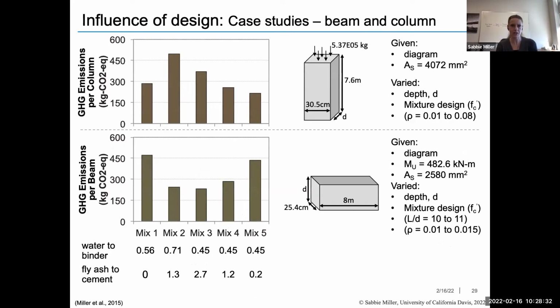So just to show you that as an example with reinforcement, these are very highly simplified members that I'm showing. We have a concrete column on the top and a concrete beam on the bottom. In this particular case, I'm showing them with the same reinforcement level. But basically what I want to emphasize here is that it's 5 different concrete mixtures with different water to binder ratios, which are what are highlighted here, and different utilization of an SCM, in this case fly ash, since that's the most common SCM used in the United States. So a higher ratio of fly ash to cement for these mixtures here, slightly lower one at the other end, and 0 fly ash used in this first mixture.